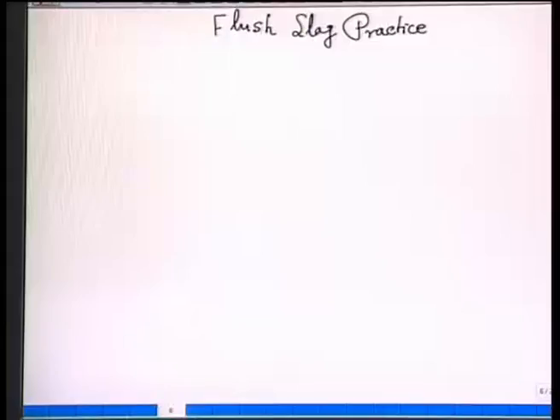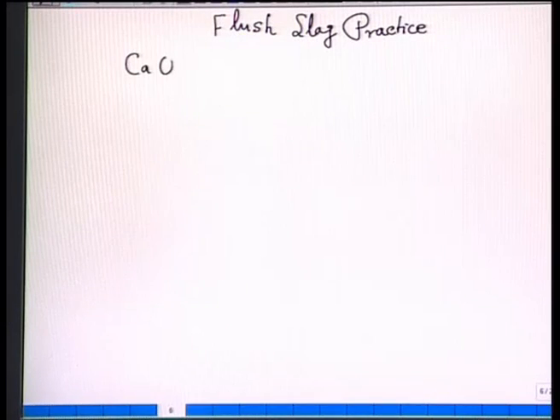How it is done? Oxidizing slag of the meltdown stage is drained out, bath is deoxidized with ferrosilicon or ferromanganese, and eventually by aluminum. Having done this deoxidation process, then pulverized coke and burnt lime are added into the bath. Now, this calcium oxide reacts with carbon under the action of the arc, because arc has a very high temperature, and it produces calcium carbide plus carbon monoxide gas. Calcium carbide is a very strong desulfurizer.